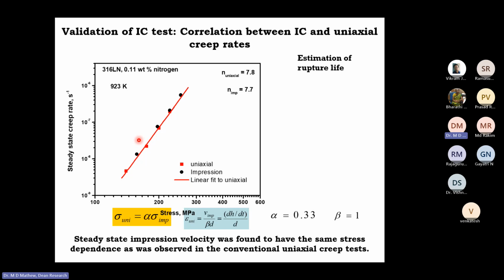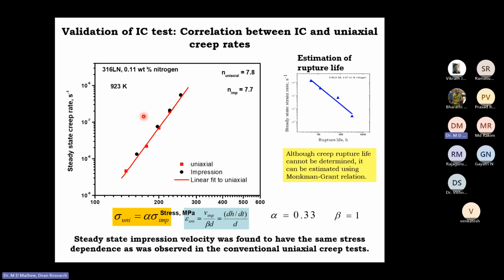But one thing that is missing in an impression creep test is you don't have any idea about the fracture life of the material, which is a very important property in creep test. So how do we do that? There are certain methods. One is using the very well-known Monkman-Grant relationship. This is a very well-established relationship between steady state creep rate and rupture life for a large number of materials. So once you have the steady state creep data, you can always, using the Monkman-Grant relationship, derive the rupture life data. So although impression creep test does not lead to rupture, you are able to generate the rupture data.